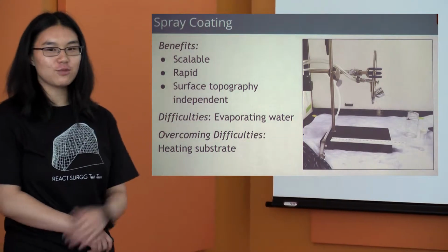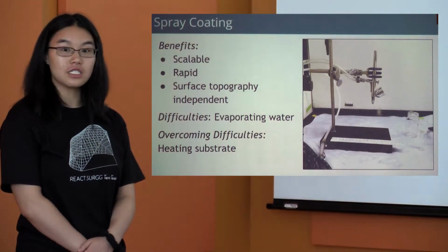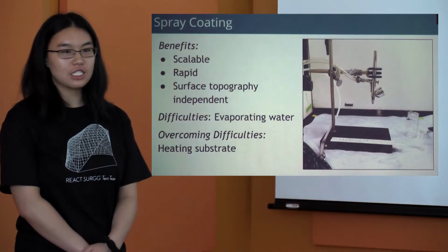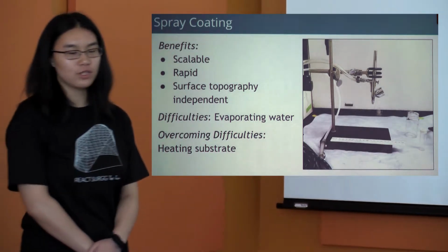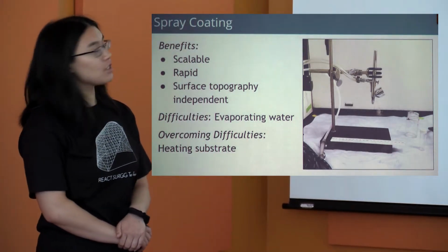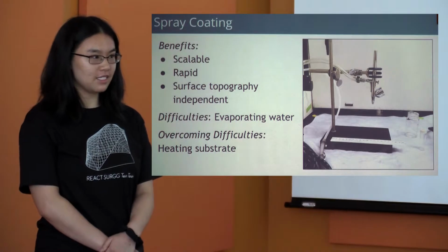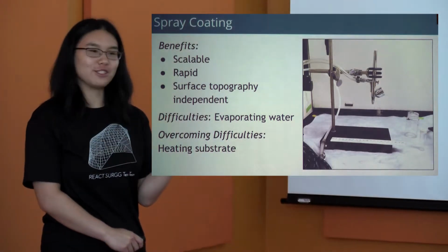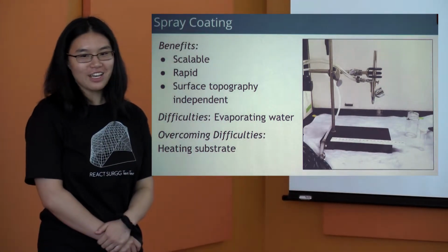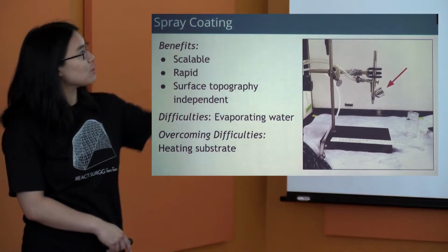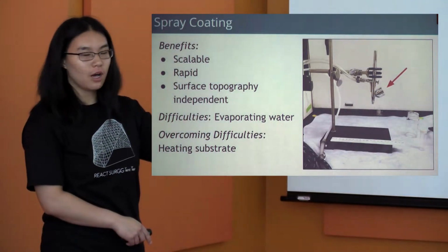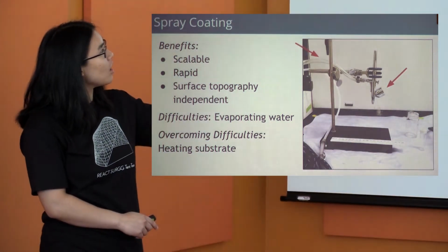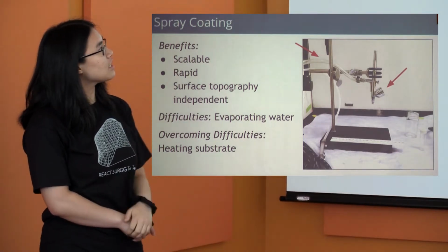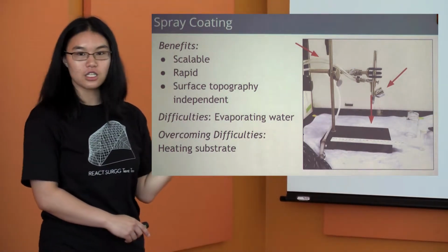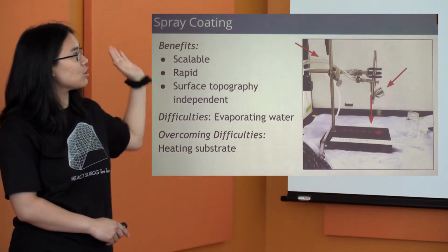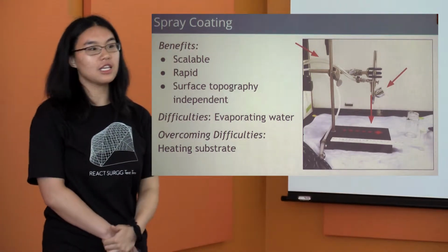Considering this, we chose spray coating as our method of delivering these coatings. This is due to the benefits. It's not only scalable and rapid, but it's also surface topography independent, thus allowing us to essentially deposit our coatings onto whatever we want. As you can see in this, the method is just to put the solution in that area. We feed air into this tube over here. This atomizes the solution and allows us to run our substrate underneath and thus coat it.